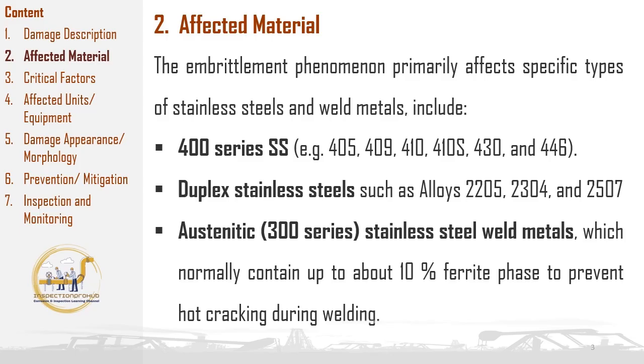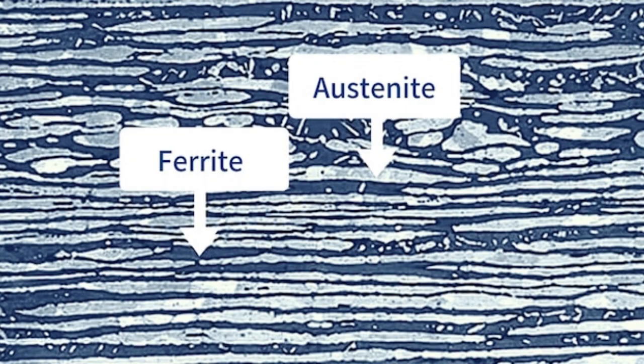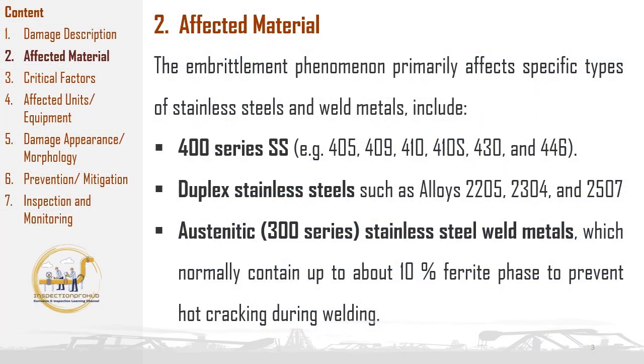However, when exposed to intermediate temperatures in the range of 600 to 1000 degrees Fahrenheit, these alloys become prone to 885 degrees Fahrenheit embrittlement. Second is duplex series stainless steels. Duplex stainless steels such as 2205, 2304, and 2507 combine a roughly equal mix of ferrite and austenite phases to achieve higher strength and enhanced resistance to corrosion, particularly in harsh environments like marine or petrochemical applications. While duplex stainless steels are highly resistant to corrosion and stress corrosion cracking, they can also suffer from embrittlement when exposed to temperatures between 600 to 1000 degrees Fahrenheit.